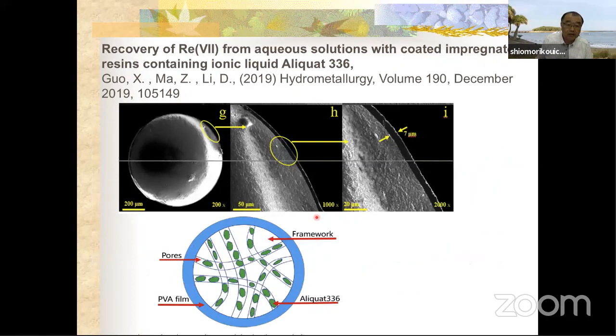The next one is an example of coating by PVA. PVA coating was done on the surface of the particle, and a quite thin PVA layer was formed on the particles. The extractant contains small pores like this, and the PVA film only lets the rhenium ion pass through. Selective separation was done using this type of particle.